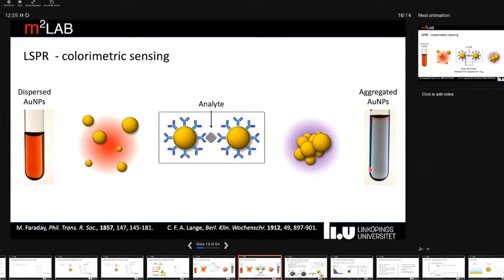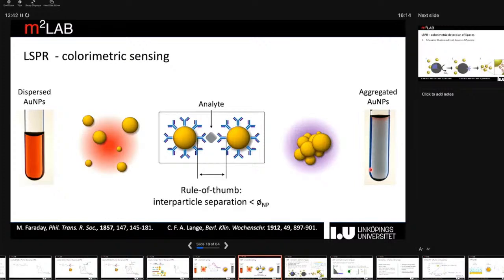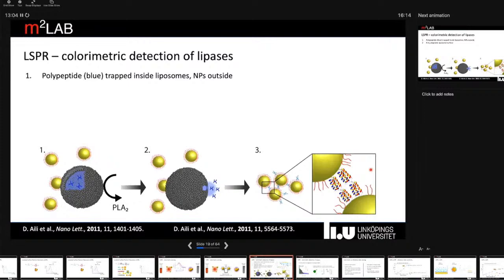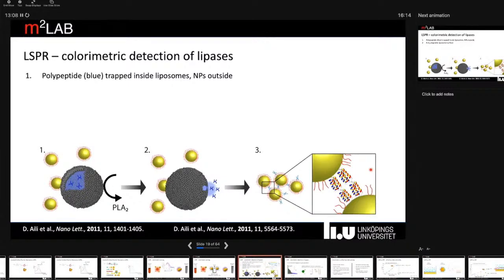But it can also be used for more specific biosensing, as we think of biosensing, where you actually have a biorecognition element that triggers aggregation or deaggregation of particles as a result of binding of the analyte. And this can be done in many different ways. And there are a few limitations, but one of the main limitations is that you have to end up with particles that are close enough to get this optical coupling, which means that they usually need to end up with a separation less than the diameter of the particles. We, and many others, have investigated various ways to use this phenomenon for biosensing.